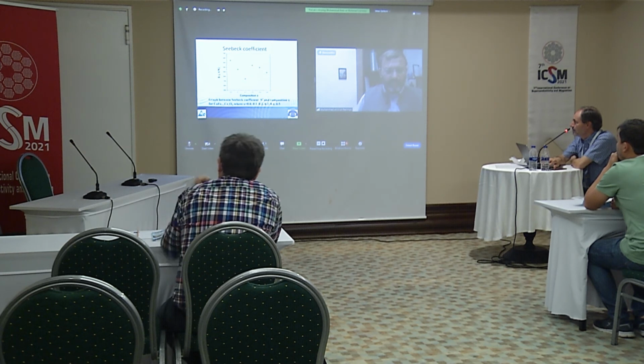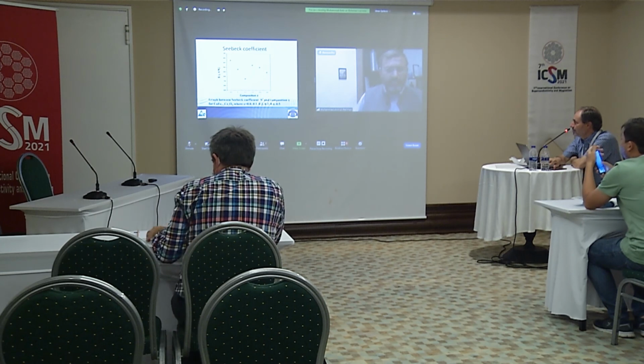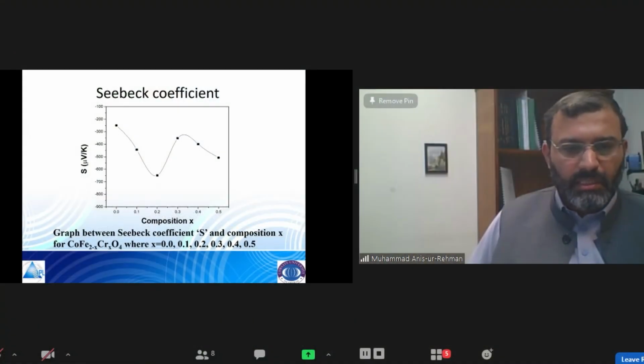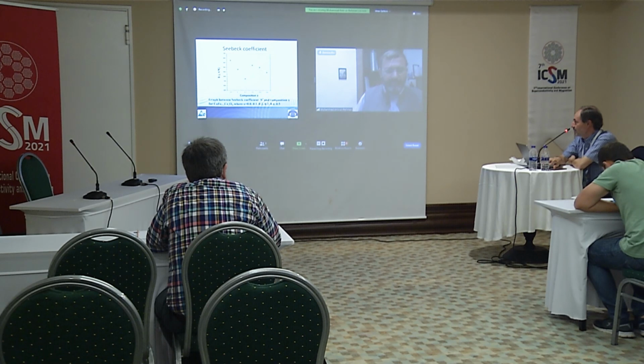Actually, the variation in the crystallite size is not uniform as we are increasing the dopant concentration. It depends upon many factors. Due to the strains and other issues, there is a non-uniform trend in the crystallite size of the material, so that is reflected in the Seebeck coefficient as well. Because this is a polycrystalline material, you may have an effect in the intragranular part, but also in the intergranular junctions between grains. You could have some concentration of impurities, impurity phases in there. Yes, but you have not been able to characterize it, I guess, whether you have an excess concentration between grains, for example.